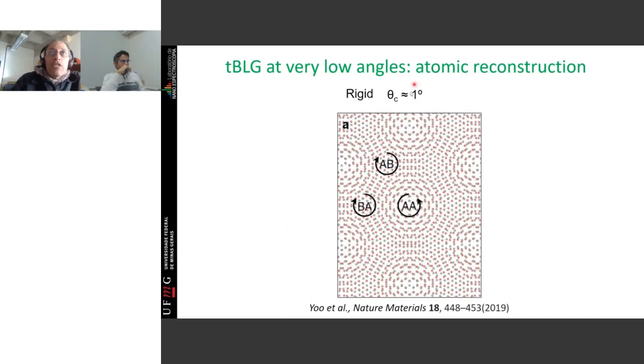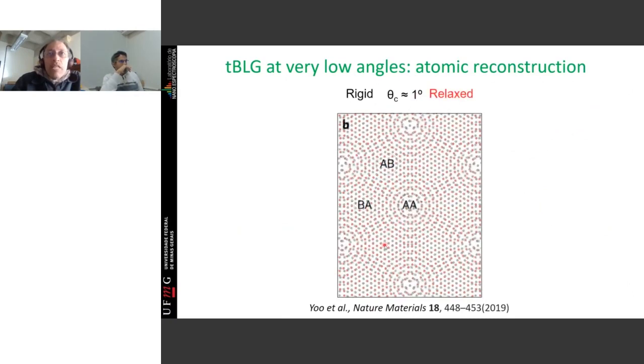What happens if the angle of rotation is too small is that this situation is not stable, and the material will naturally rotate back to the AB stacking, okay? The AB stacking is that one where this atom falls on the middle of the hexagon of the other. However, the direction of rotation will be different in this area and in this area, and consequently, in the middle, there will be a domain wall, and this will be a strain soliton. It will be a soliton of strain, okay? It's a region of high strain for you to move from rotation counterclockwise to rotation clockwise. And in the middle, you have this AA structure, okay?